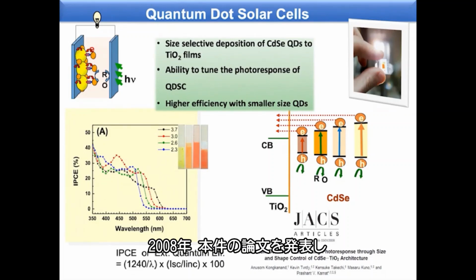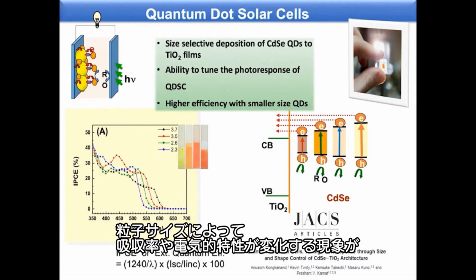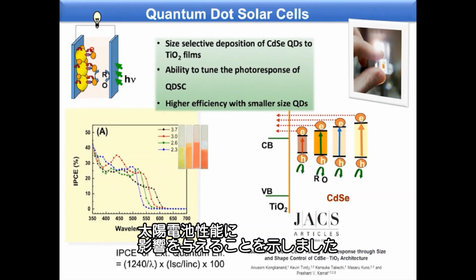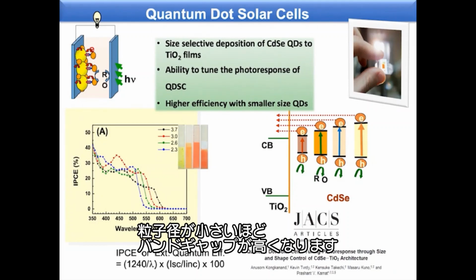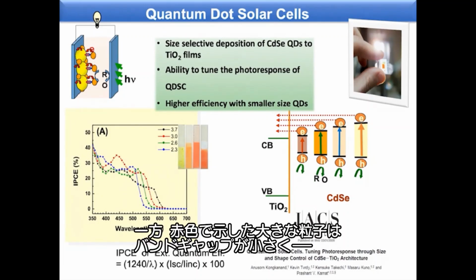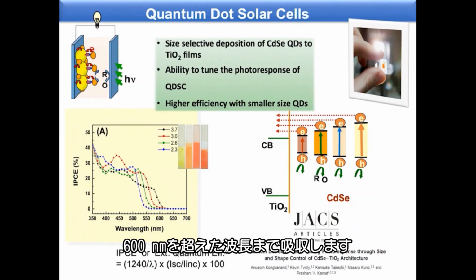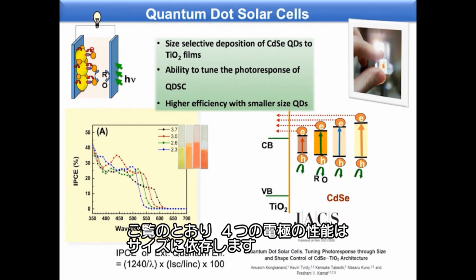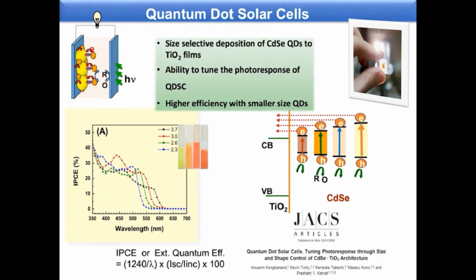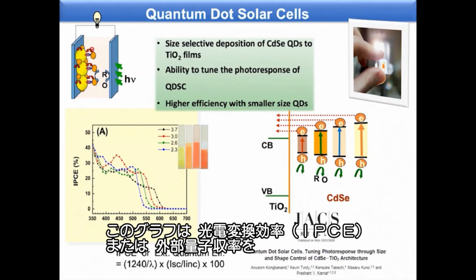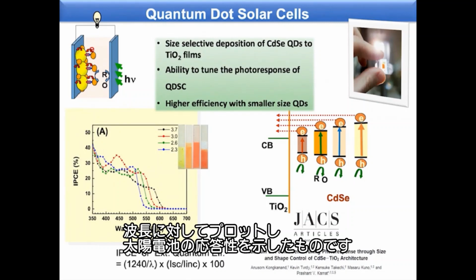This was originally published in 2008, where we showed that the size quantization effect, that is the dependence of absorption and electronic properties on the size, is reflected in the performance of the solar cell. The smaller size particle has a higher band gap, which is represented in the yellow color, and that absorbs high energy, whereas the larger particles are red in color, they have a small band gap, and they absorb all the way beyond 600 nanometers. As you can see here, these 4 electrodes show the size dependent performance, and this plot, what is referred to as IPCE, is incident photon to charge carrier efficiency, or external quantum efficiency, plotted against the wavelength, basically showing you the response of these solar cells.